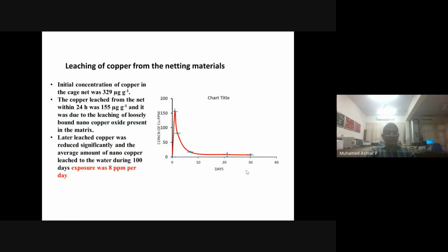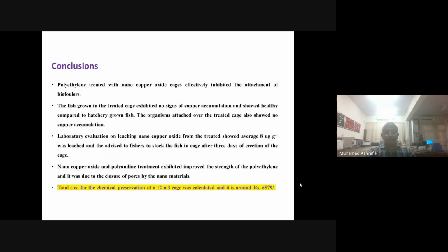And then with the leaching of copper, we always talk about leaching. We first saw that in the initial first 1-2 days, the leaching is comparatively higher. After that, it becomes very low, because most of the leached material was from the loosely bound copper over the polyaniline.